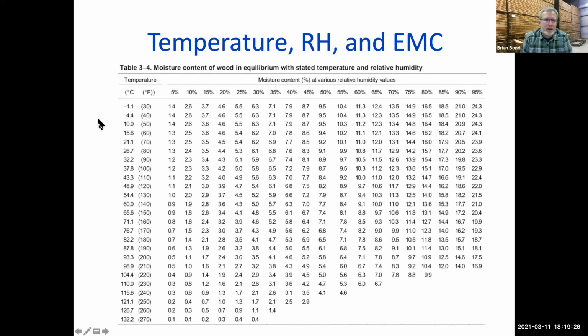And so let's just pick an example. If I'm air drying lumber and it's 70 degrees outside over here on the right, 70 degrees, I scroll over to what my relative humidity is on the top. So it's probably about 65% relative humidity, 70 degrees Fahrenheit, 65% relative humidity. I'll scroll over here. I can get a 12% moisture content if it stays out there long enough, okay? And you can use this chart to look at that relationship.